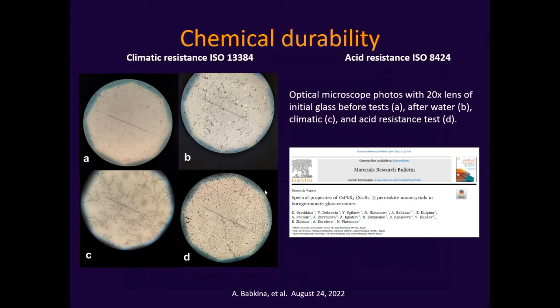And of course, when we are talking about unstable systems, namely perovskite nanocrystals, as I said before, in solutions they are not stable. In the form of monocrystals, they aren't stable. So stable, but not very good, really. When we put them inside of the glass, we can make measurements of their chemical durability according to the ISO, International Standard Organization, that standardizes all optical materials that are used in optical schemes. So it's for all optical materials that are used in massive production.